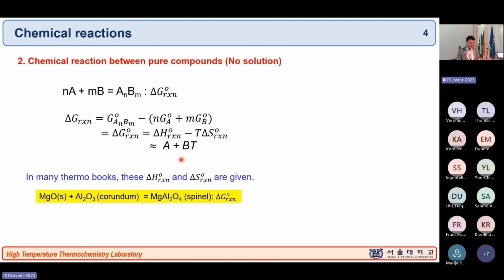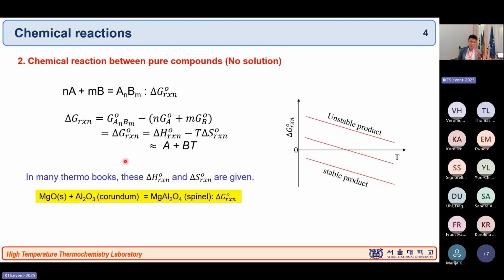Okay, so when you're actually talking about MgO plus Al2O3 become MgAl2O4, okay? I mean, we know this Gibbs energy of reaction, and if you plot it with the temperature, depending on the chemical reaction you plot, you can have a graph on the top, or a graph in the middle, or the red line in the bottom, okay? So when you have the chemical reaction, delta G of reaction, by the way, in this case, is the same as delta G naught of reaction.